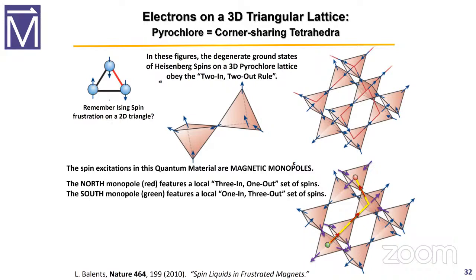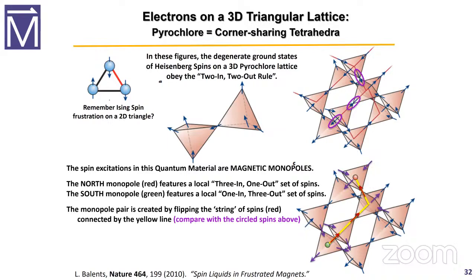So how does it do that? The north monopole is in red. It features on that tetrahedron three in and one out. So here you've got one, two, three in and one out. The south monopole here in green has one in and three out. And all you have to do to get from here to here is flip a few spins. So by merely flipping these three spins, so they point up to the right instead of down to the left. Here it's up to the left instead of down to the right. So you can pair create with very little energy just by flipping spins, because the difference in energy in flipping a spin is essentially zero.